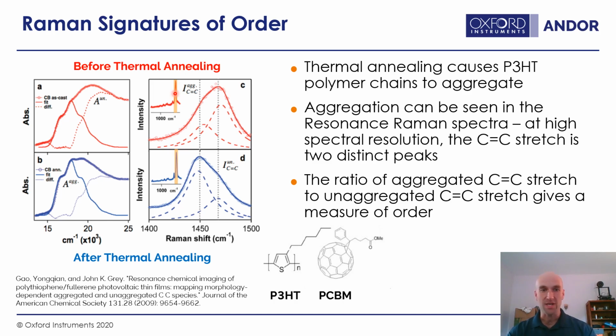This window here is only 50 wave numbers wide. So we're looking at a shift of just a few wave numbers here, something like 10 wave numbers or so. And this peak that appears to be one is actually two superimposed. One of them corresponds to aggregated P3HT chains, the other one to unaggregated P3HT chains. So that can also be seen in the absorption spectra here, and I don't want to get too deep into what's going on here because it's a long story. Happy to discuss it further, but the key point was that our group, and by our group I specifically mean the first author here, Yongqian Gao, hope he's doing all right out there, realized that you could use this as a metric for aggregation, and it's a very fast and very, I hesitate to say easy, but a clear sign of the state of the polymer that you're looking at.